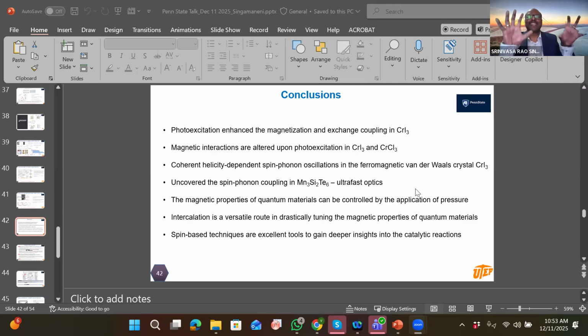All right. I did not disclose that part of the information because we are writing a manuscript, but in simple words, I'm going to tell you this. So we chose molybdenum sulfide with different crystallite sizes, and we observed the lowest crystallite size compound shows the highest amount of hydrogen gas, and we tracked that using advanced electron spin resonance measurements. And what we found was that the lowest crystallite size has a large number of sulfur vacancies, and though that compound has other paramagnetic centers like Mo3+ or oxygen coordinated, only the sulfur vacancy related active sites could lead to higher hydrogen evolution reaction. So that's all I can tell now. But after maybe 2 weeks, you will see our manuscript online. So there we are going to provide almost all the details. I hope that answered your question.